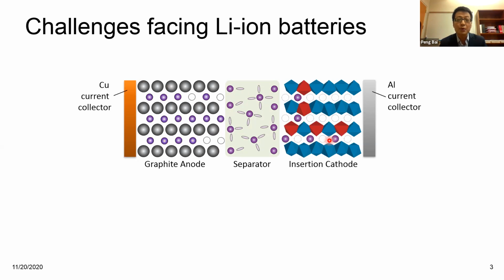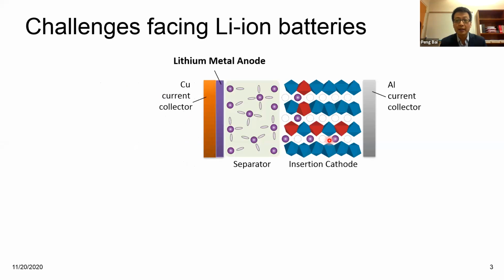What if we can remove that volume? One way to do this is to completely remove the graphite electrode and then allow the lithium ion to be reduced into the metallic state, creating a thin layer of lithium metal. So in this case, you save the volume by nearly a half without sacrificing the energy you stored in the system, because all the ions are still in there. They can still stay in the cathode and be reduced on the anode. So this sounds like the simplest way to significantly increase the energy density of a battery.